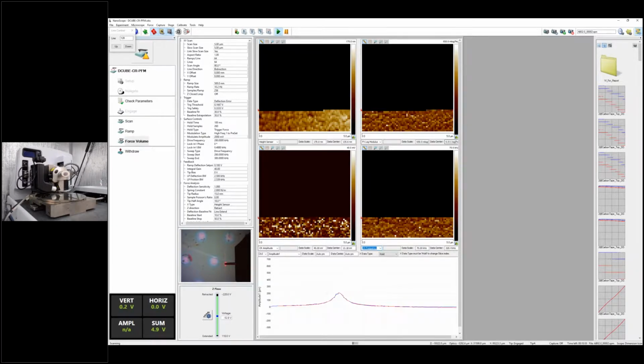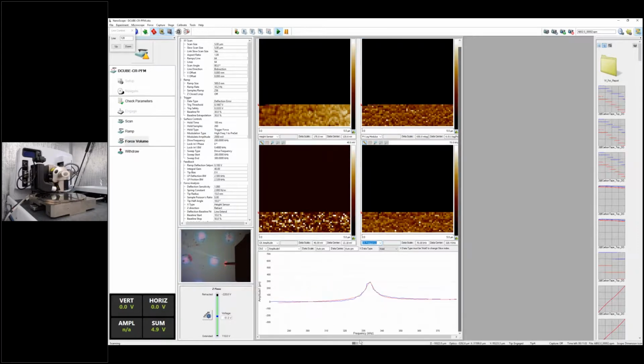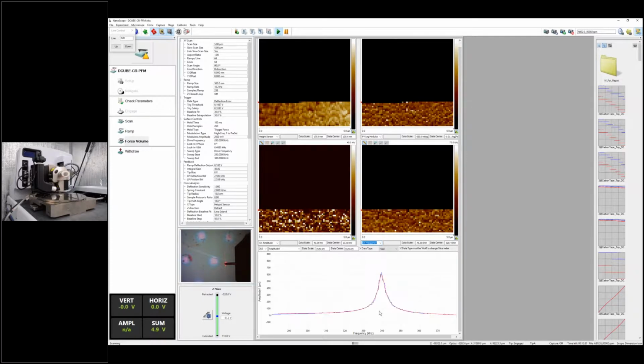So within this range, and also from the lifetime holding spectrum, you can see the frequency jumps quite a lot, maybe from 310 all the way up to 340 or something like that. So the window is roughly about 30 kilohertz. If you don't use this kind of real-time tracking for the contact resonance, you can imagine that at each pixel, the response is boosted with a different kind of enhancement factor. Because when we use contact resonance, we basically take advantage of the Q factor, or the quality factor, of the cantilever to boost this piezo response. And if you are at a different location of the contact resonance peak, then the effective Q factor will be different, which means your data is not actually normalized.